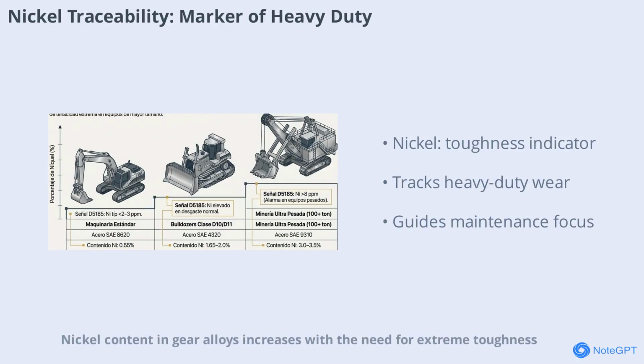Nickel content in gear alloys increases with the need for extreme toughness, especially in larger equipment. By tracking nickel levels in oil analysis, we can infer not only the alloy type but also the operational demands placed on the machine. Higher nickel readings often point to wear in components designed for heavy-duty service, helping pinpoint the source of metal particles and guiding maintenance priorities.